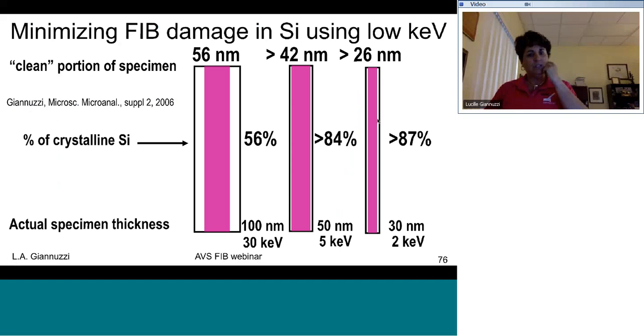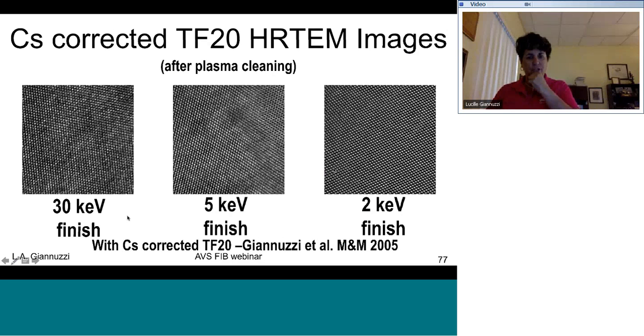So the idea, and what I like to do then, is to start with the sample thick, generally about 200 nanometers. That will just give you more pristine sample to work with in the center of your sample. Get it nice and thin using 5 kV, and then do an endpoint. And this reduces the sidewall damage to only a couple of nanometers on each side, and then do your final polishing at 2 kV or less with either the gallium, xenon, or your offline argon ion. Okay. And there, of course, is again work we did years ago showing that you can go to a 2 kV finish and definitely improve the image quality.